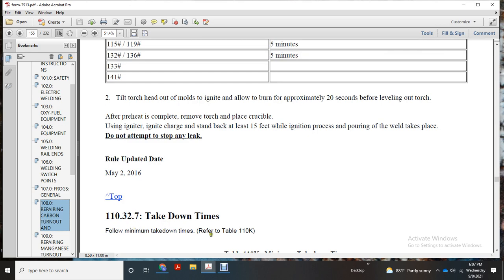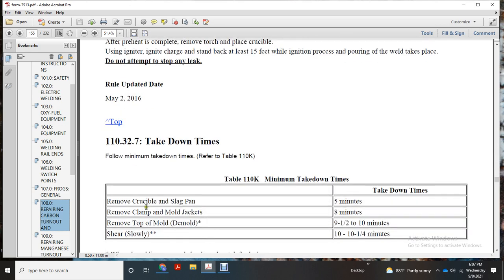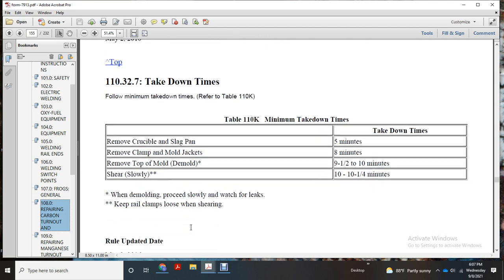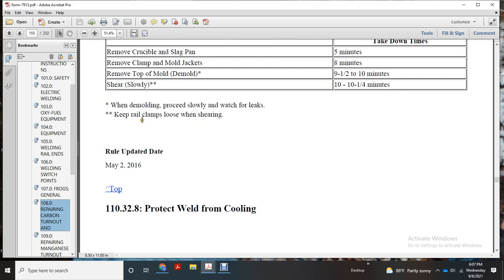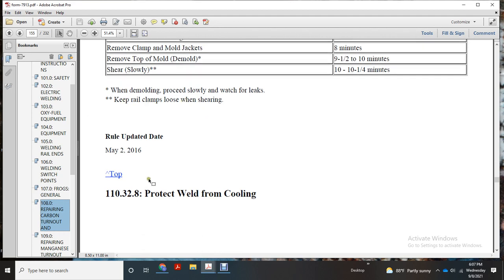Takedown times: follow the minimum takedown times for table 110. Remove crucible and slag pan at 5 minutes. Remove clamp and mold jackets at 8 minutes. Remove the top mold and demold at 9.5 to 10 minutes. Shear slowly at 10 to 10.25 minutes. When demolding, proceed slowly and watch for leaks. Keep rail clamps loose when shearing.